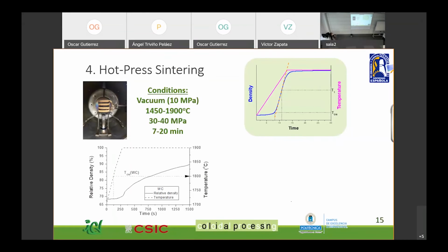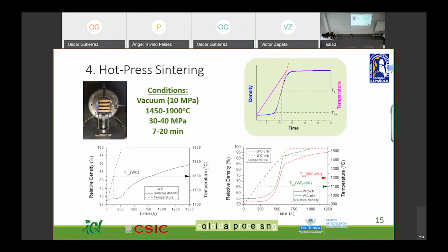Under these criteria, we carried out first a binderless tungsten carbide sintering process, and we did the same for the mixtures with commercial and nano nickel. As we can appreciate here, well, it is very difficult to see because the graph has been shortened, but in this case, both the times and sintering temperatures are really long and high. This didn't happen for the mixtures with nickel, especially with nano nickel, whose results show a clear improvement because the sintering times are much shorter and the sintering temperatures lower, by almost 500 degrees.